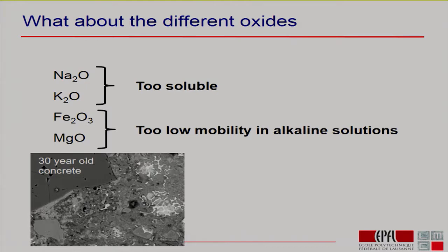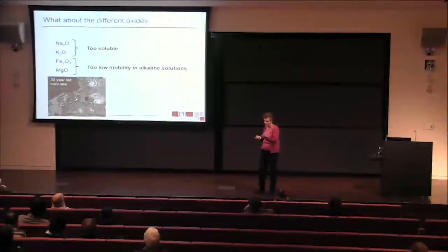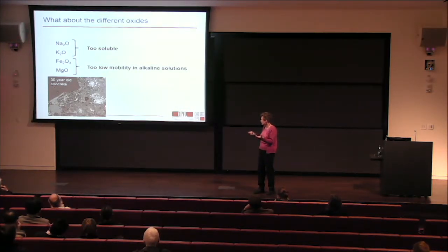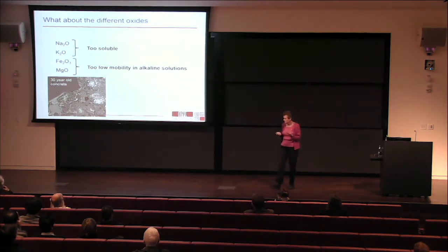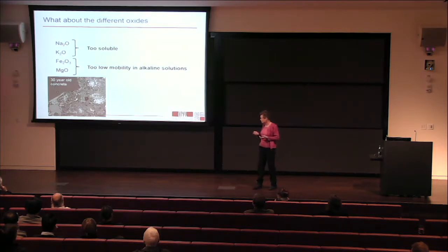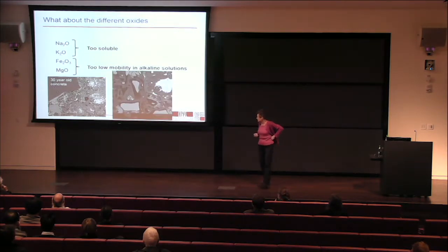They were in the cement grains when it went into that concrete, and the other elements, the calcium, the aluminium, have all moved around and filled in the space. So you see we now have products between these grains, but the iron has just stayed in exactly the same place. So again, it's not doing any harm, but it's not really doing any good in terms of giving us strength in the system. And it's the same story with magnesium.